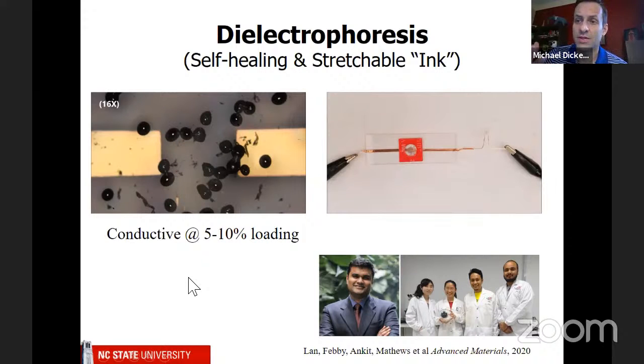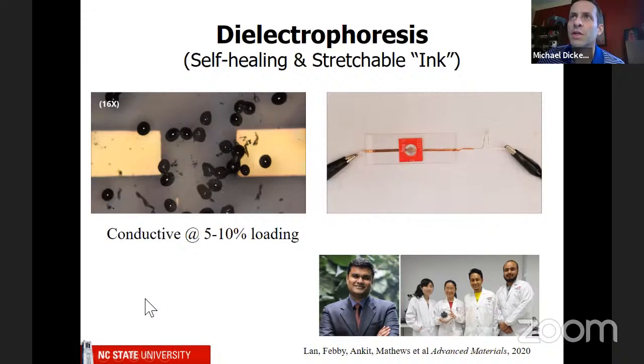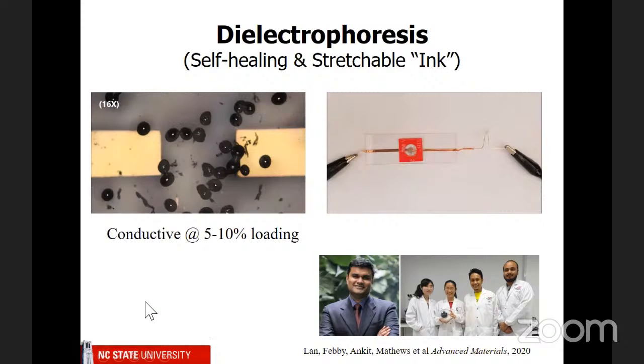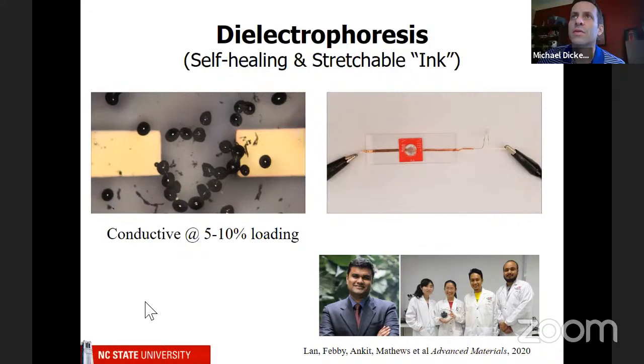Basically, we made liquid metal particles, and you can see them here. They're these spheres, and they're sitting in silicone, which is a liquid, an oil-like material. As you can see, there's not enough particles here to form a conductive path, so this is a perfect insulator. However, if you apply an electric field between these two gold electrodes, if you watch carefully, you'll see that the particles merge together. This is again called dielectrophoresis.